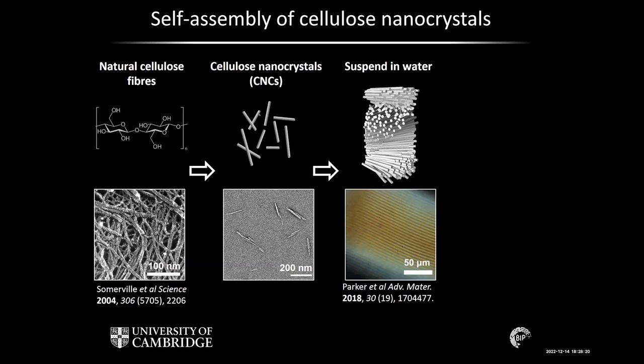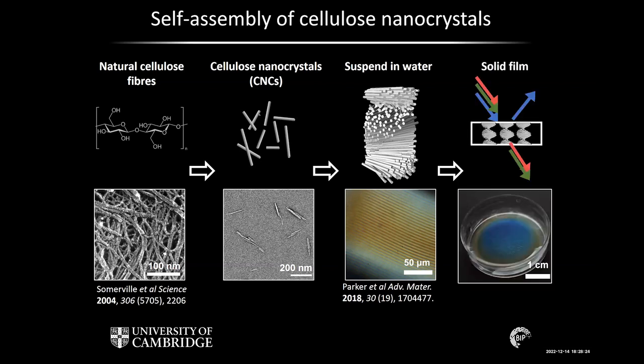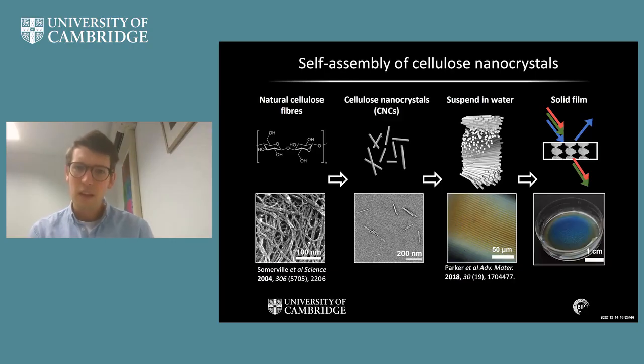And so then if we take this liquid suspension and dry it out, we can create a solid structure which preserves this periodic arrangement of the CNCs. And what we find is that due to constructive interference at some wavelengths of light, some colors of light and not others, it appears blue in reflection because the blue light is reflected while the other wavelengths of light are transmitted. So actually, this phenomenon has been studied for a couple of decades now, but there's a few things that we still don't really understand about what's going on in this process. And something that's really bugged me throughout my PhD is essentially why the CNCs always choose to form this left-handed structure. They only ever form a left-handed helicoidal structure, not right-handed, and it's not immediately obvious where this breaking of symmetry, where this chirality or this choice of handedness is coming from.